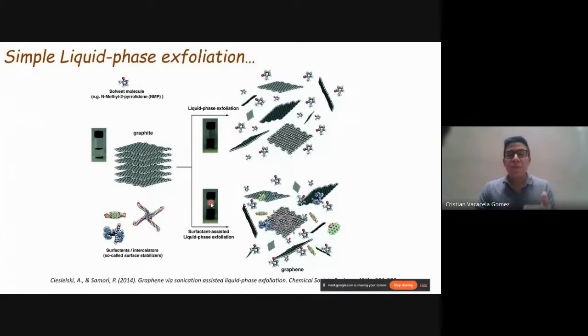And a similar thing can be done, for example, in water. But what is the problem in water? The problem in water is that the surface tension of water is higher compared with the surface tension of graphene. So if you want to match the surface tension between them, you need to reduce it. How can we do that? We can introduce graphite and water, and to stabilize and reduce the surface tension, we can introduce polymers or surfactants. There are other techniques to produce graphene, few layer graphene dispersions, but remember that is different from graphene oxide or reduced graphene oxide samples.